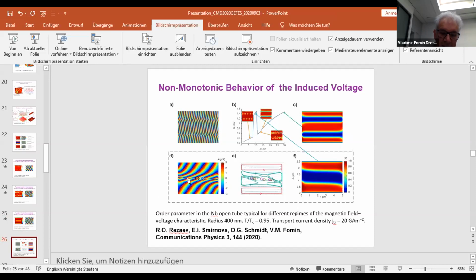If we look here at the winding numbers of each of these defects, which we saw in the previous slide, one of them is a vortex and another is an anti-vortex. And they move over this locus of their nucleation. Naturally, a vortex moves to the right until it meets an anti-vortex of the next pair and annihilates. An anti-vortex moves to the left until it meets a vortex from another neighboring pair and annihilates.